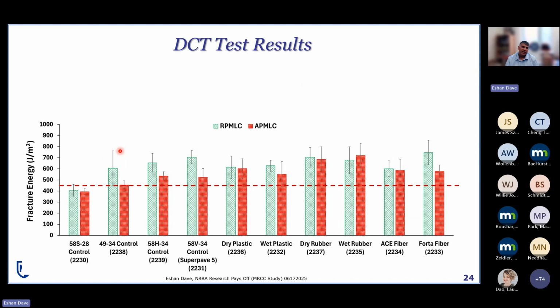The disk-shaped compact tension test fracture energy values. So I put just a line as a reference at 450 joules per meter squared, just as a reference line there, because that's the value that has been used in the past, also for designing mixtures in cold climate conditions with this particular test and this parameter. So as we can see, the control actually failed to meet that initial threshold. All the other ones well exceeded that.